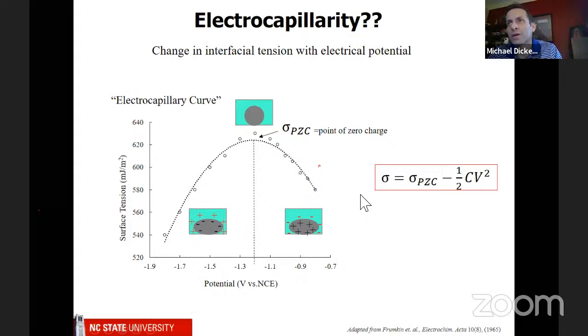And so the equation that describes the shape of the surface tension is: the surface tension is equal to the surface tension at the point of zero charge, that's the peak of this parabola, minus 1/2 CV squared. If you remember from freshman physics, this is the equation for a capacitor. And it's describing the effect of this charge on the energy of that surface. Because the voltage is squared, it doesn't matter if you apply a positive voltage or a negative voltage. Either way, you get the same effect, and you should get a symmetric parabola.